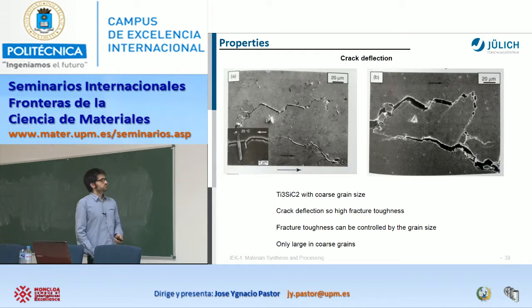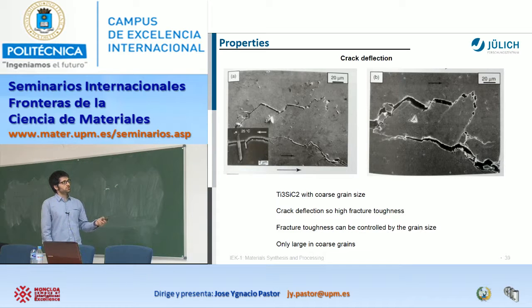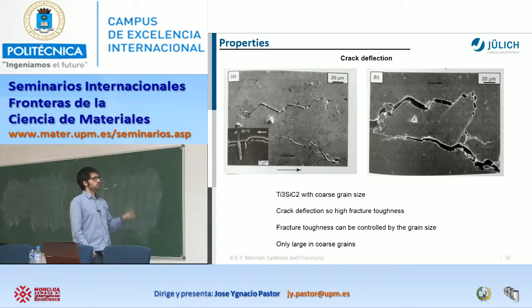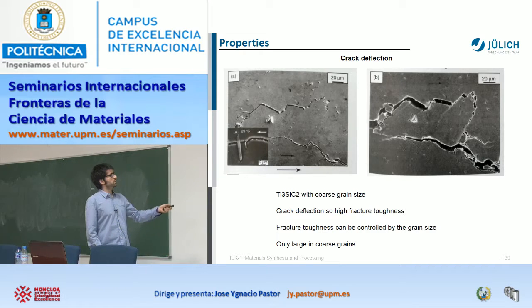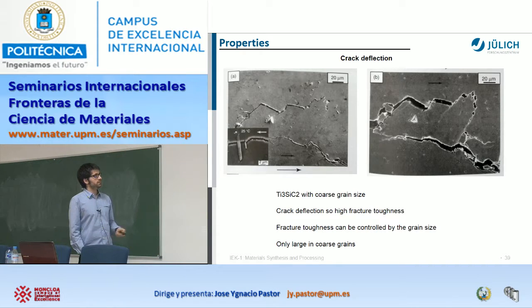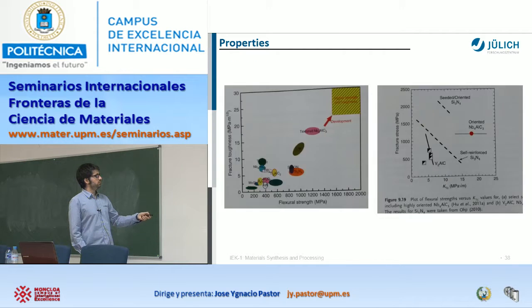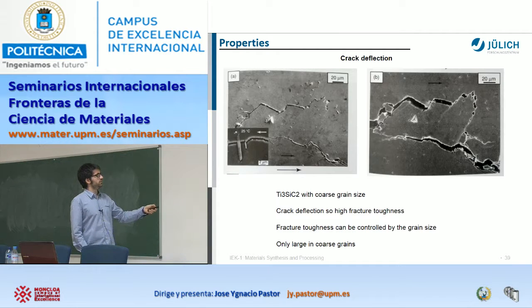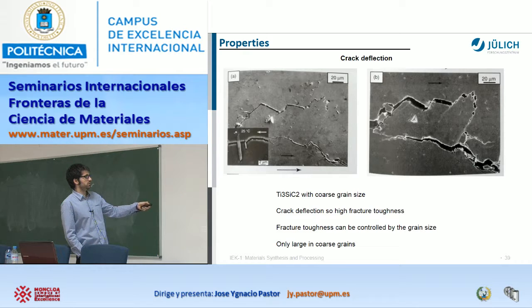Okay, and what is the reason? It is this crack deflection that I barely introduced at the beginning. I mean, the crack is not just one crack that continues through your material as if nothing happened. Here it is all the time deflecting and following these layered structures, okay, and moving. And also, for example, here you see one of these MAX phase grains doing some mechanisms, okay. Well, here more detail about some part here or here probably, about how they deflect, and then you start to lose your energy.